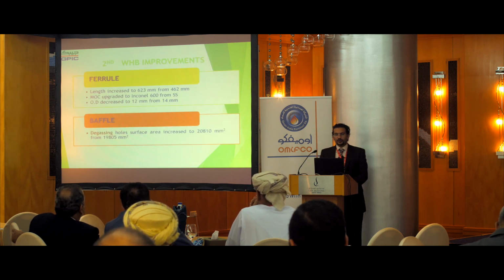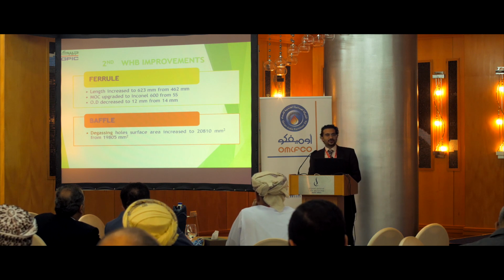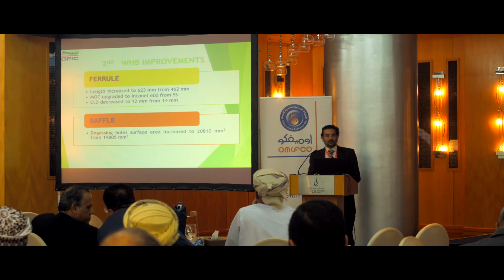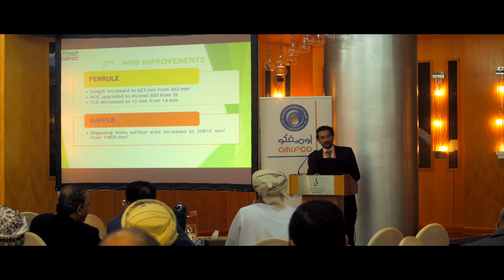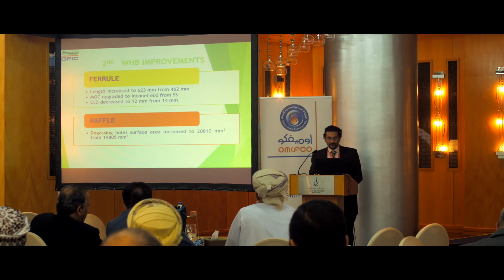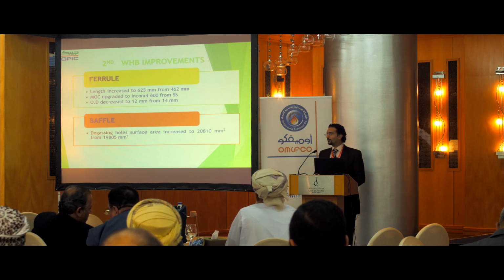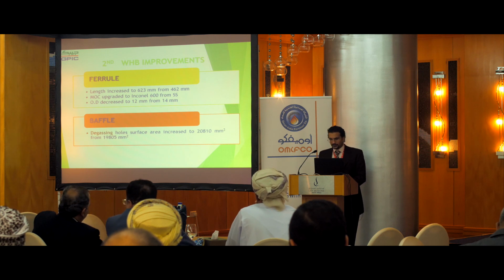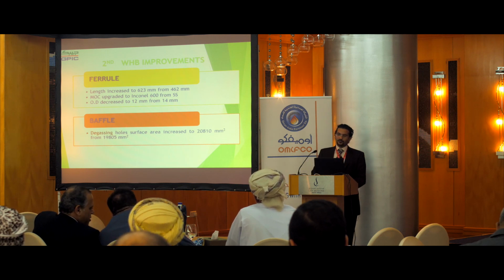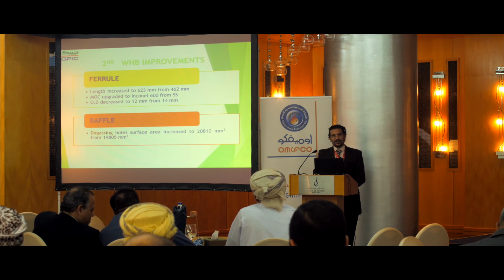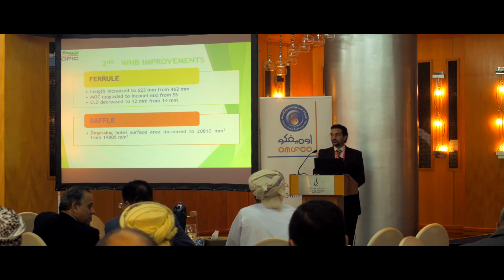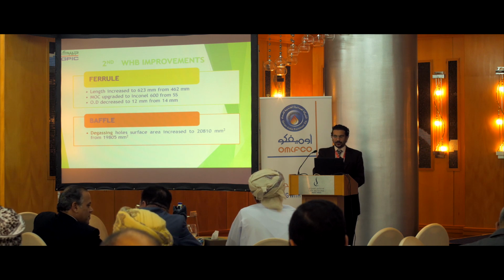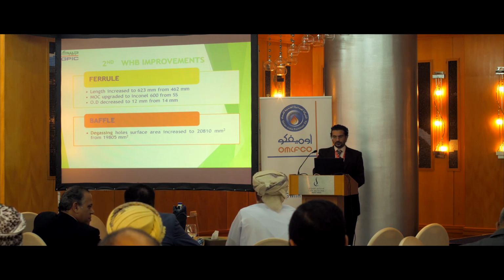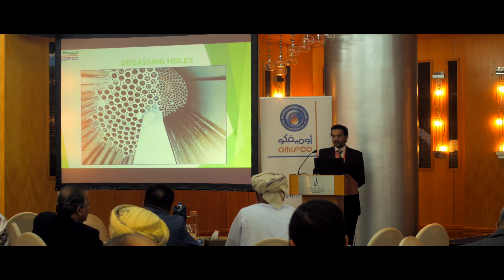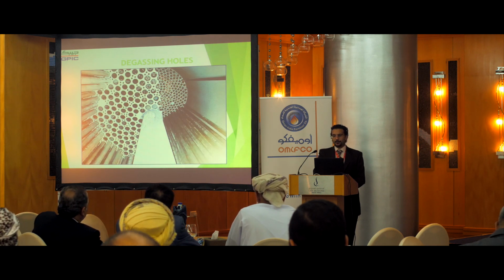For our second waste heat boiler, there had to be, of course, improvements after many years. The length of the ferrule was increased to 623 millimeters from 462. The MOC, material of construction, was upgraded to Inconel 600 from stainless steel. And the outer diameter decreased to 12 mm from 14 mm. As for the baffle degassing holes, the surface area was increased to about 20,810 millimeter squared. These are the degassing holes as the steam exits.